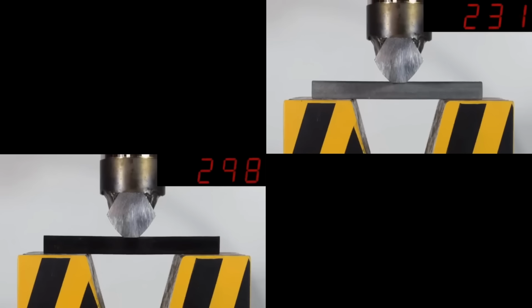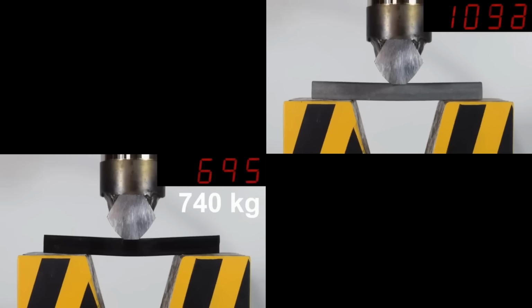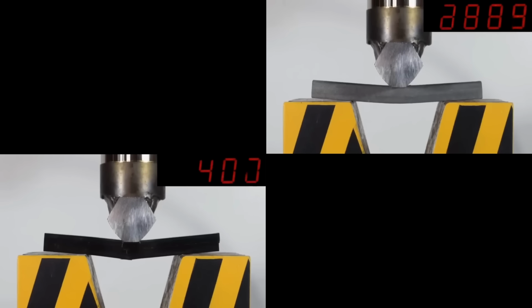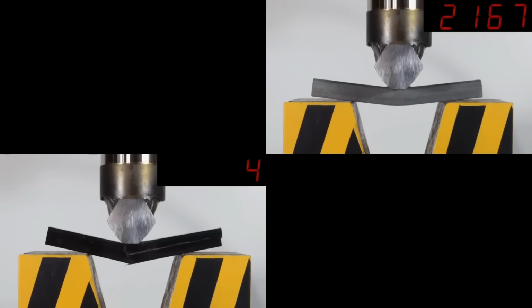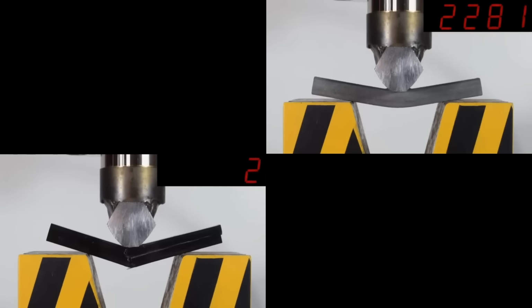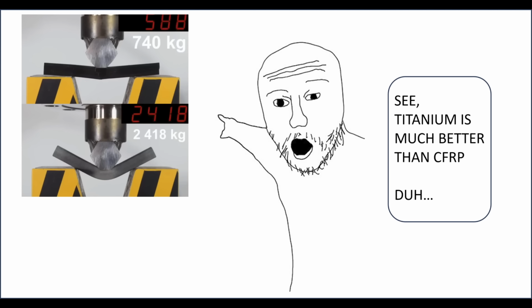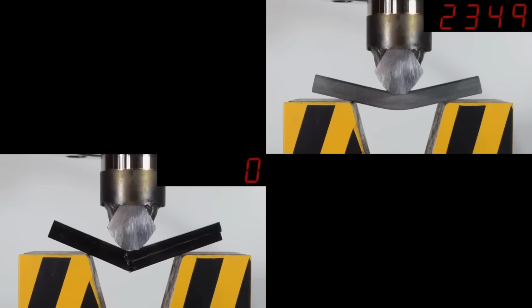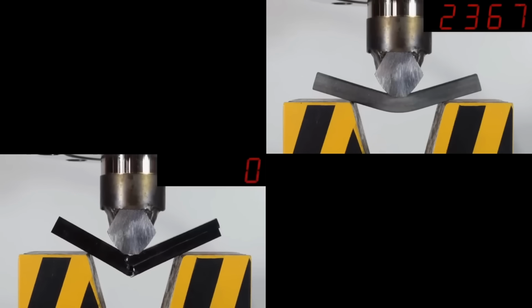This video shows a 3-point bending test of a CFRP and a titanium specimen. The titanium specimen carries about 3 times the load until failure compared to CFRP, and therefore people concluded that titanium is much better than CFRP. But this video doesn't show the whole truth from an engineering perspective.